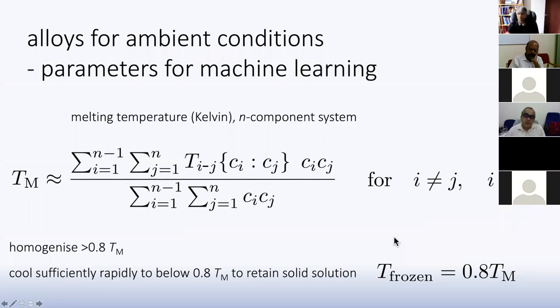So let's have any number of components in our high entropy alloy, but we will only look at binary combinations of all those alloys. So, for example, this might be iron, this might be nickel, and this is the melting temperature of an iron-nickel combination for the concentrations of iron and nickel in our high entropy alloy, multiplied by the concentration of iron and concentration of nickel, and then divided by the concentration of iron and the concentration of nickel, and we do this summation over all possible binary combinations, however many components we have in our high entropy alloy. This calculation is done for the entire binary combinations. So iron nickel, iron cobalt, iron chromium, iron whatever, and then cobalt nickel, cobalt iron, etc., etc. And then that gives us the overall melting temperature of the high entropy alloy.